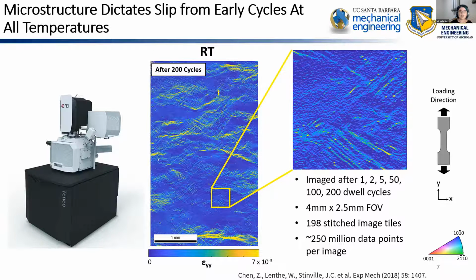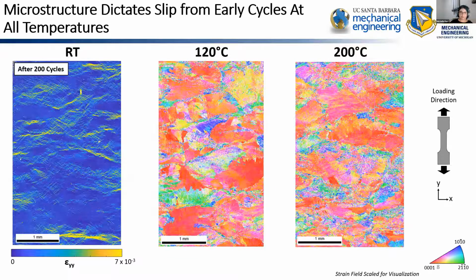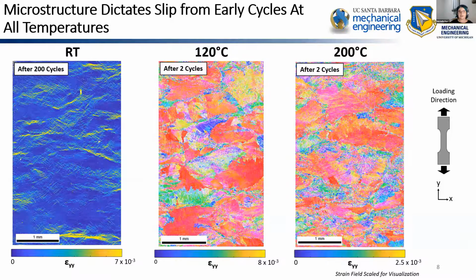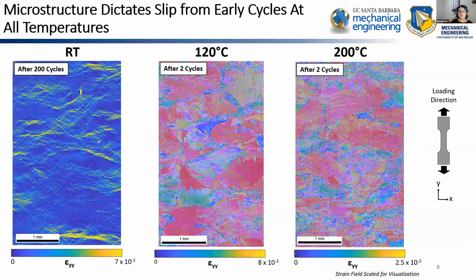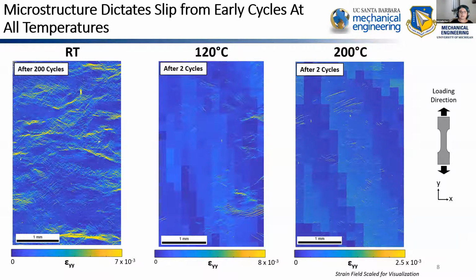And so we ran that experiment at room temperature, and then we repeated the same experiment in an ambient temperature of that 120 C case, which we know should have the peak dwell debit, and our 200 C case where we expect to not see much dwell effect. And again, we ran those after two cycles and then continued to cycle up to 200 cycles.